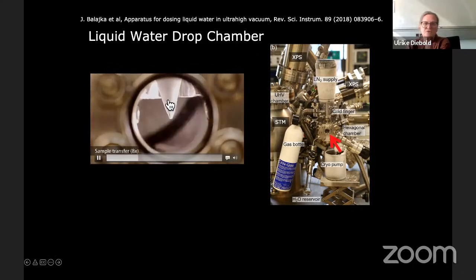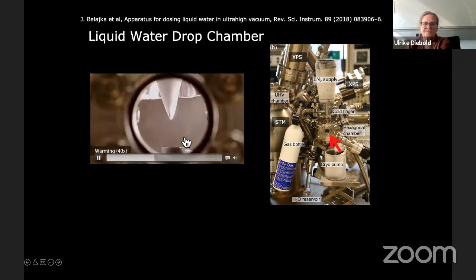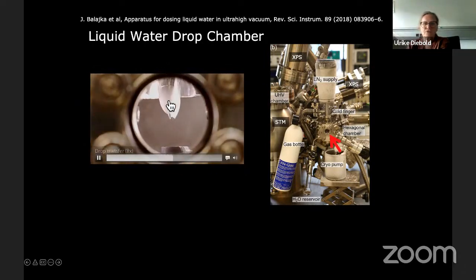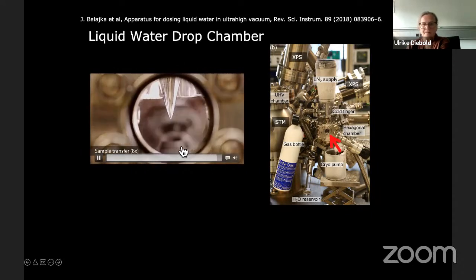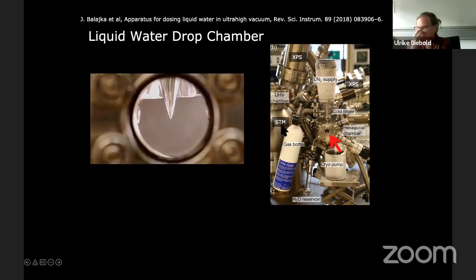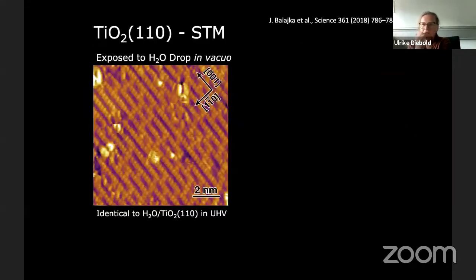So once the icicle has formed, you can put in the sample, close again, and let this ice warm up, make a water drop, and put the water drop on our sample. Then we pump out with a cryo pump until the water is gone, open up again, take the sample and stick it in the scanning tunneling microscope. If you do it in this way, then we can get surfaces where we can get real atomic resolution.